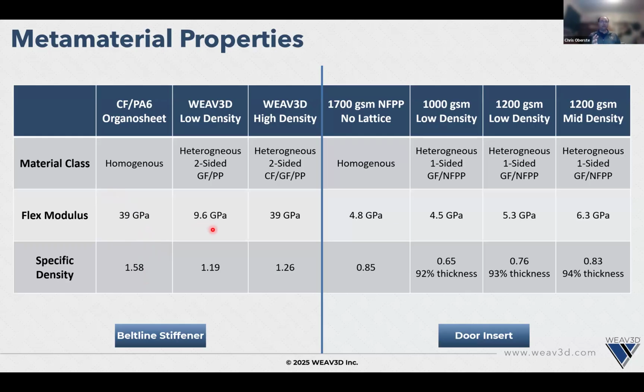This is also a 2-sided design, so the lattice is on both top and bottom of that sheet that you saw. But the density is really low, about 1.19. And then when we go to a hybrid glass and carbon fiber 2-sided, we now are back up at 39. So the idea being that in the area where we need the performance, we are directly matching the original organo sheet. But in the areas where we don't need the performance, we can reduce that density, save cost, save weight. And even then, we're still at 1.26 despite matching the original organo sheet.